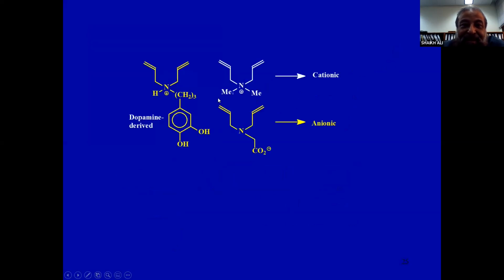And here is another one. This is catechol, dopamine derived. With a cationic monomer, we can get a cationic polymer. With an anionic monomer, we can get an anionic one, and they can combine together to give a coadsorbate complex. Complex coadsorption, because the cationic and anionic will precipitate out, and that will have a lot of dopamine catechol moieties that can do their job, like attaching onto the surface like molecular sieves, adhesives.